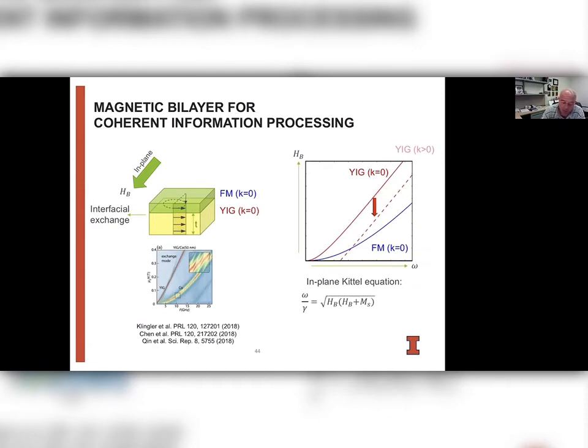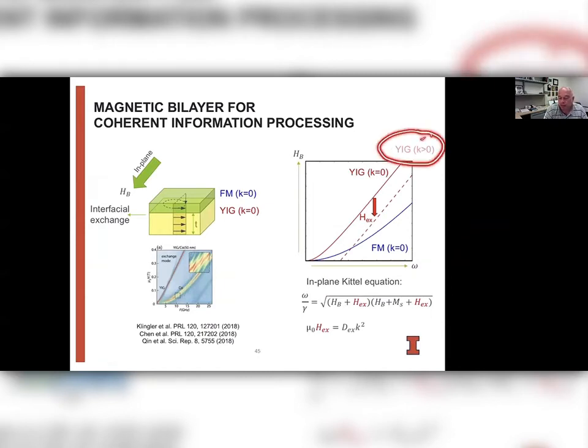And one way this can happen is by using a mode that has a finite wavelength. And when you do that, then you essentially have an additional exchange contribution to the resonance frequency of your spin wave mode. And this additional exchange field contribution goes quadratic with the wave vector.